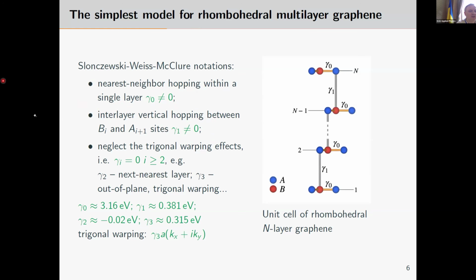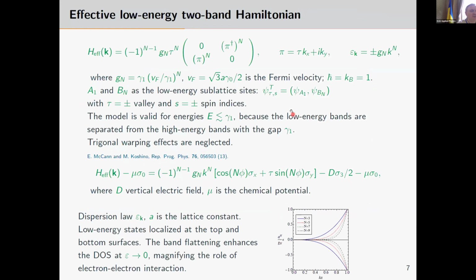But in the simple theoretical model, we just restrict to those two hoppings. So this is the unit cell of n-layer graphene. Neglecting the trigonal warping effect, we obtain a very simple effective Hamiltonian. You see that this is just a 2x2 matrix in pseudo-spin space. For n equal to 1, this is monolayer graphene. N equal to 2 is the rather well-known case of bilayer graphene.